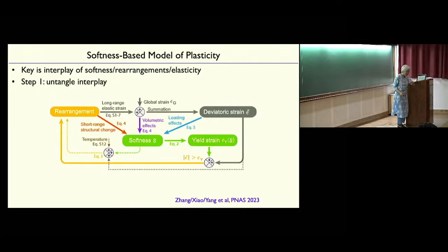Now what we're going to do is construct a lattice theory, similar to what we did before for the glassy dynamics. But now elasticity is critical, we have to include elasticity. This is complicated, but the point is that when I have a rearrangement, I do a bunch of things. I create a contribution to the strain. But I also have the short range structural change that I mentioned before that changes the softness. The long range strain also affects the softness.